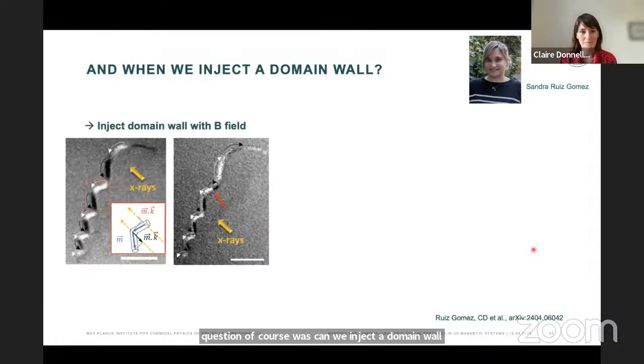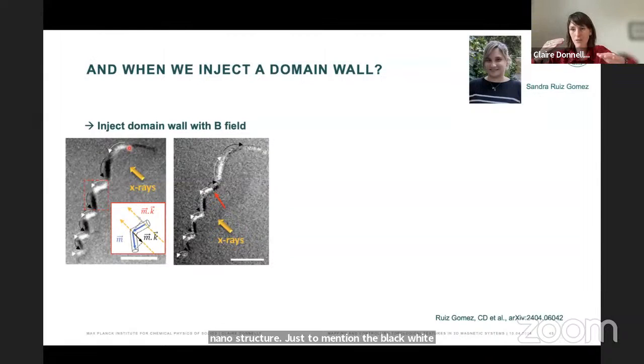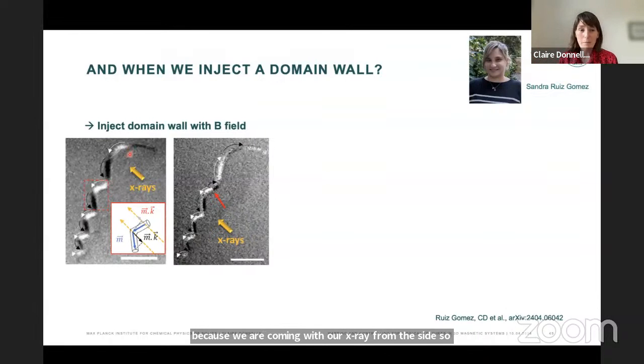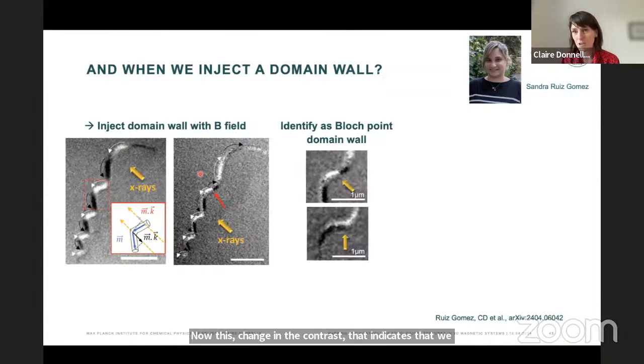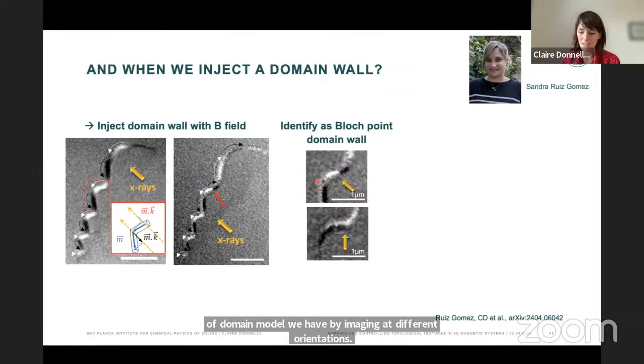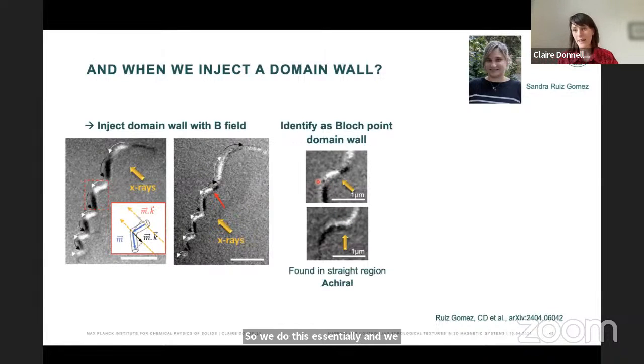So the first question, of course, was, can we inject a domain wall? And the answer was yes. We have here our magnetic nanostructure. Just to mention, the black-white contrast actually corresponds to a single domain state because we are coming with our X-ray from the side, so it's pointing parallel and anti-parallel, but this is purely the projection. But when we apply a magnetic field in situ along the long axis of the nanowire, you can see here at this red arrow that we have a sharp, abrupt change in the contrast. Now, this change in the contrast indicates that we have a magnetic domain wall. And we can determine what type of domain wall we have by imaging at different orientations. So we do this, and we see contrast as a function of angle that is consistent with the presence of these Bloch point singularities.